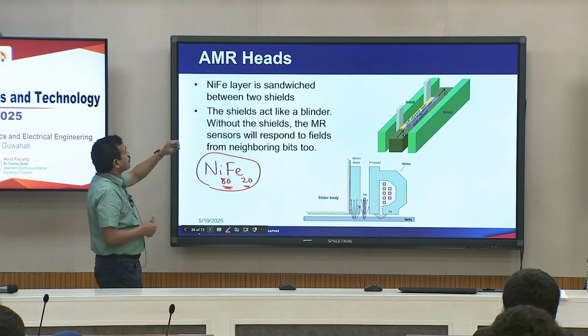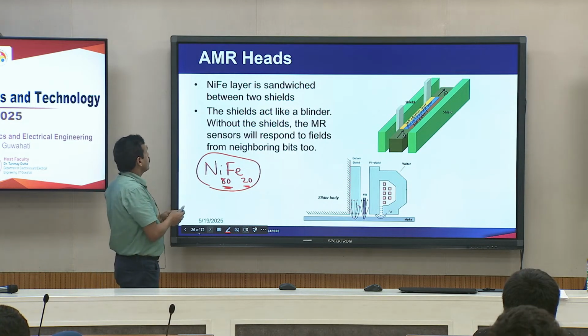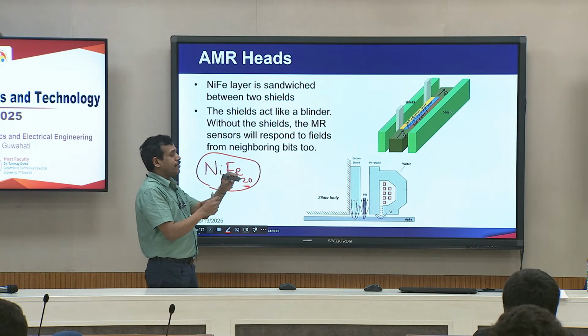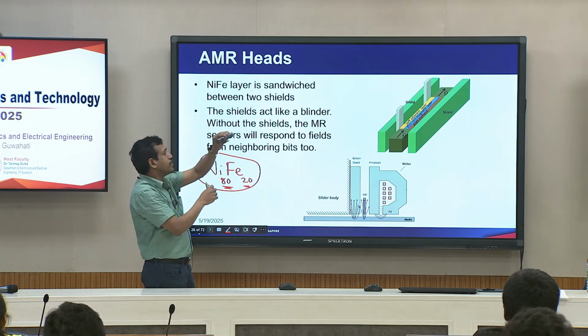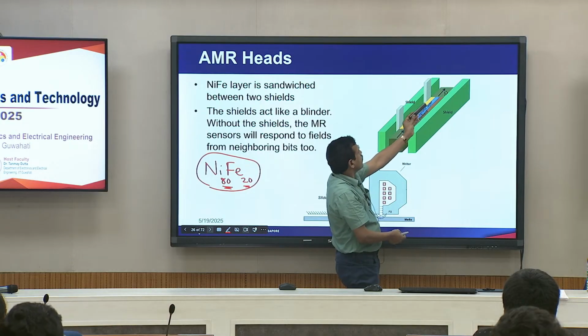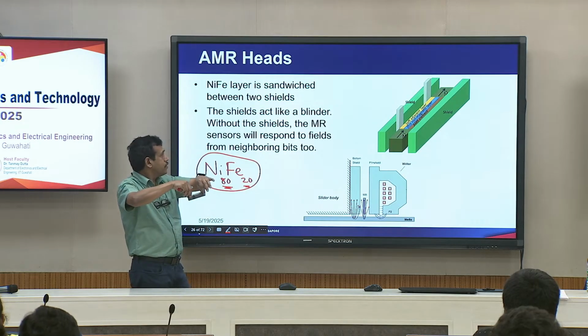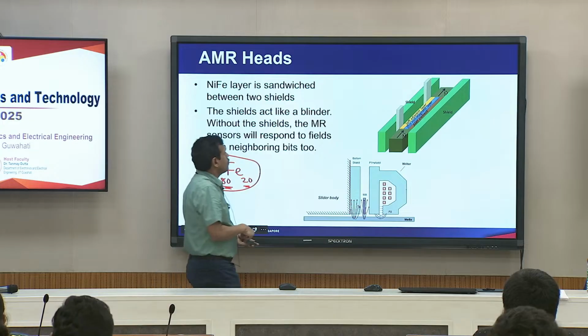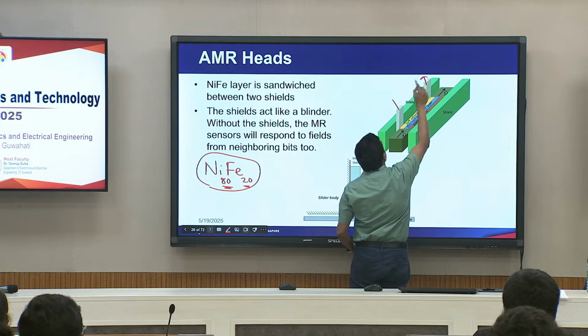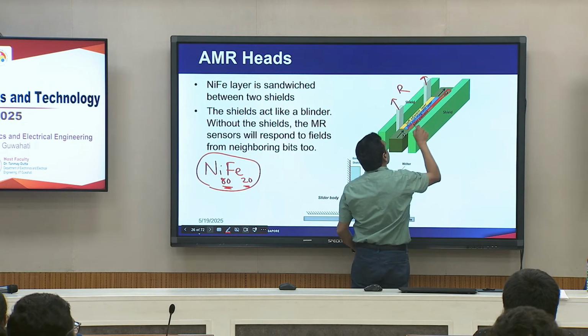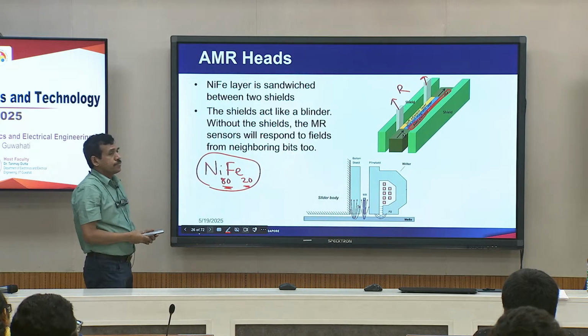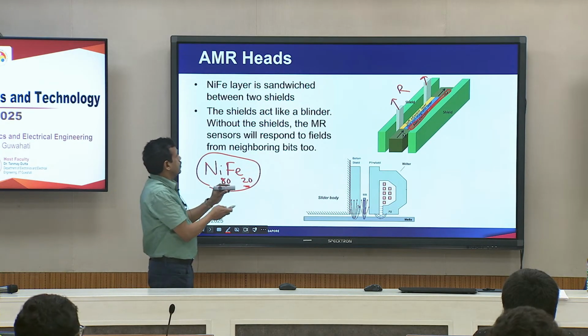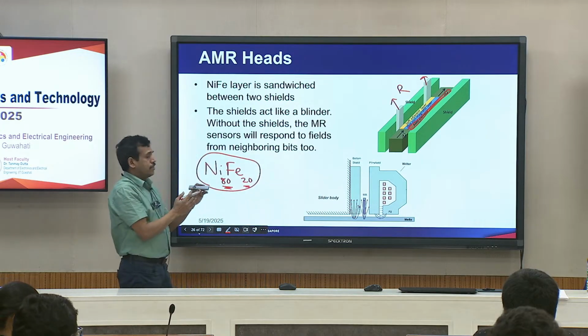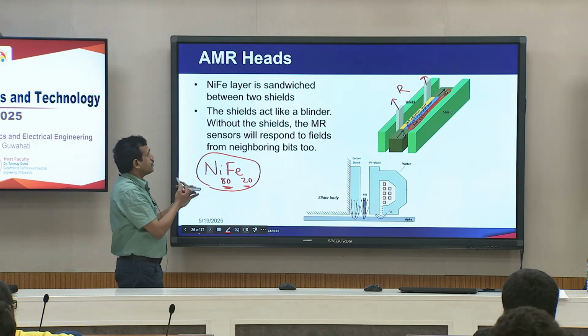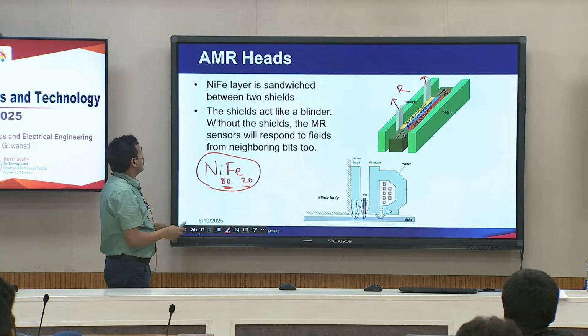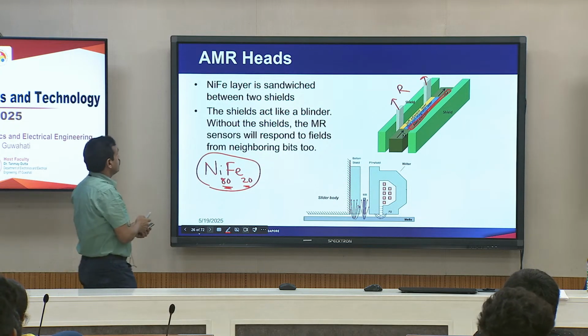So, if you want to make a read sensor based on anisotropic magnetoresistance, what you will do is make a permalloy wire patterned into some shape like this. So, the shape of the AMR element here will look something like this. Then you have two probes. You send current through the probes, then you measure the voltage. So, you use these two probes for measuring the resistance of this AMR element. As we just saw in the previous graph, when there is no magnetic field, magnetization is along a certain direction, but when there is a magnetic field, the magnetic field influences the magnetization direction. So, there will be a change in the resistance, and we are using that change in the resistance to sense information. Okay. So, later I will ask.